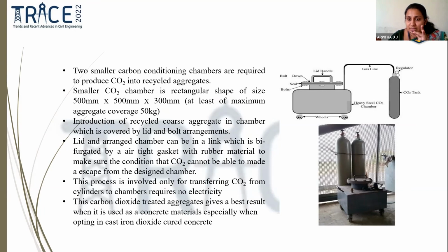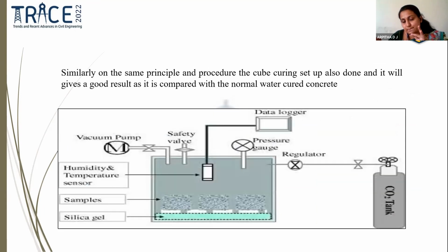Similarly, next slide. Similarly, that recycled conditioned aggregate has to be used for preparation of concrete. When concrete cubes are prepared, this chamber has to be designed, a self-designed chamber. It has to be designed in such a way that there is a vacuum pump. This vacuum pump is important to let off the carbon dioxide after curing, along with a safety valve to let off everything, and a pressure gauge with a regulator.